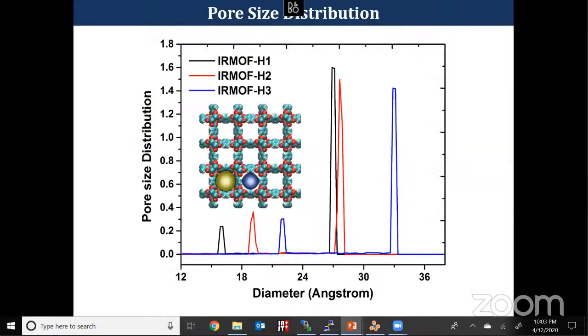So we have a crystal structure, and we need to know how the pore structure or pore size is distributed over the crystal structure. What kind of pore, whether it has a single pore or a dual pore or multiple pore sizes in a single crystal. So from the pore size distribution analysis curve, we found that this metal cluster cubic kind of MOF has two different pores in it.